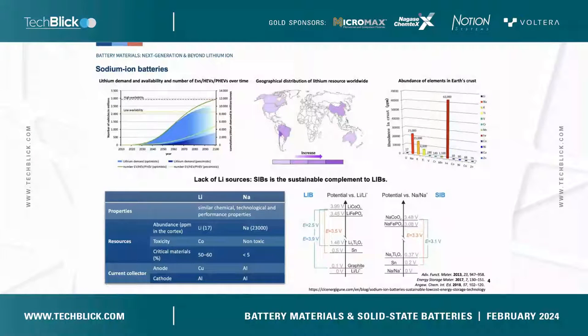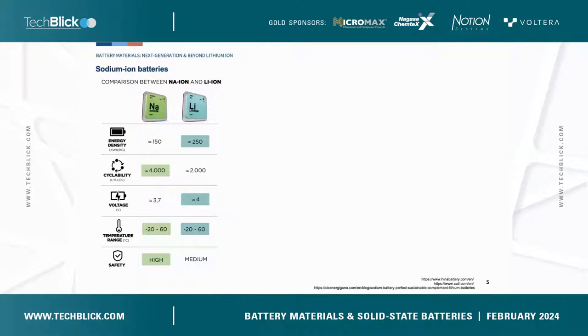There are also some exceptions — graphite is a very successful anode material in lithium batteries, but in sodium batteries it cannot perform well with pure intercalation reactions. Compared with lithium, sodium also has some advantages: apart from abundance, we can also eliminate the use of cobalt, which is toxic. For current collectors, we can replace high-cost copper with aluminum for both the anode and cathode sides. After assembling the cell, sodium batteries have good cyclability and much better safety compared with lithium batteries. The current energy density for sodium batteries is about 140 to 160 Wh per kilogram, which still needs to be increased in the future.